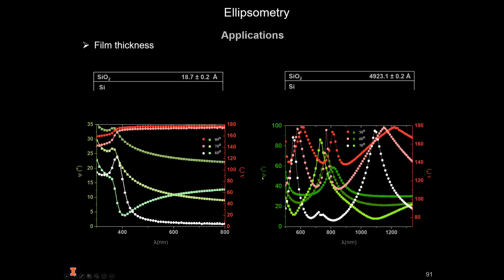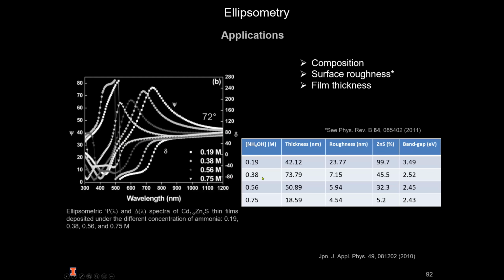Besides thicknesses, ellipsometry can be used to characterize many other properties of the sample, depending on the model you have, like composition, roughness, band gap energies, or anything that you can determine from the dielectric function of the material. Like the data tabulated here for the case of cadmium zinc sulfide films that had different compositions.